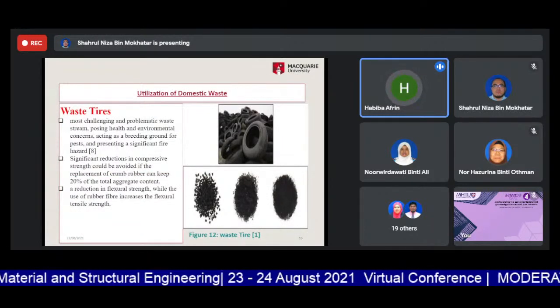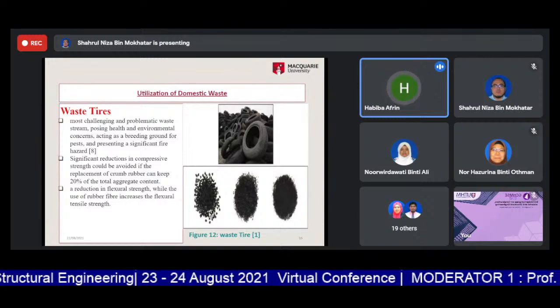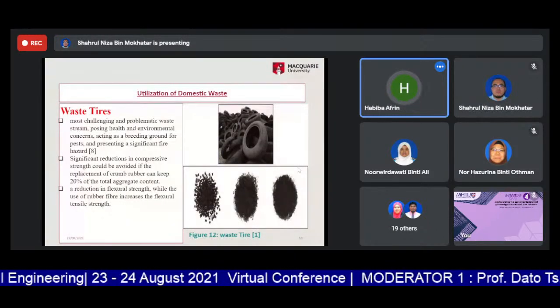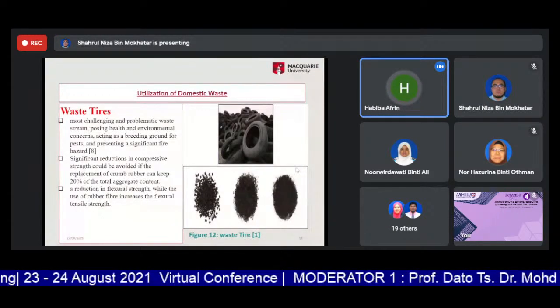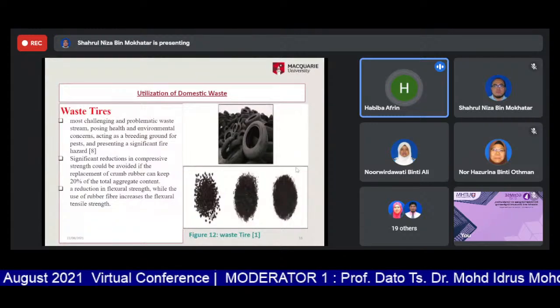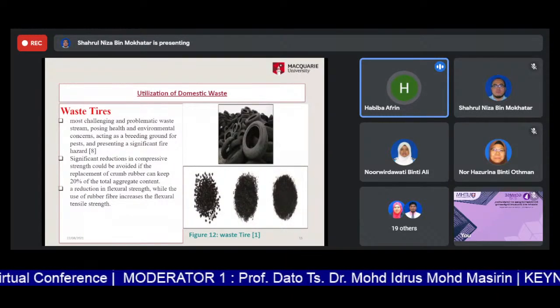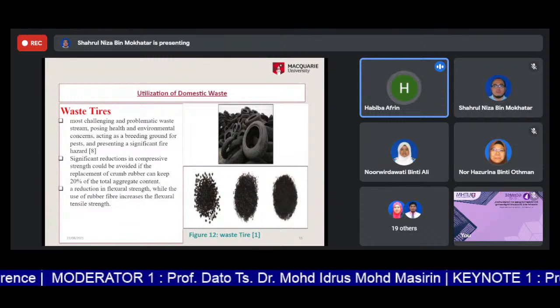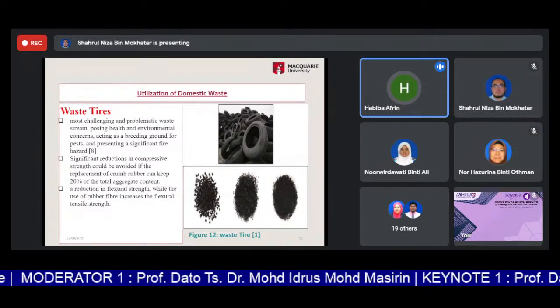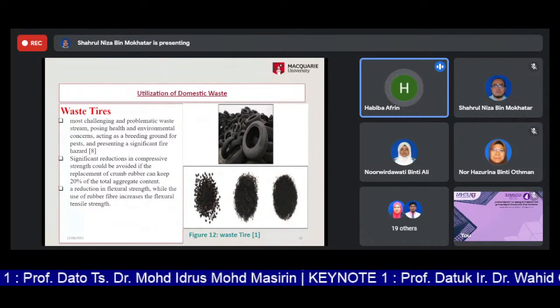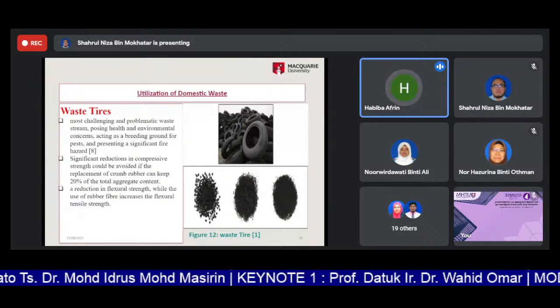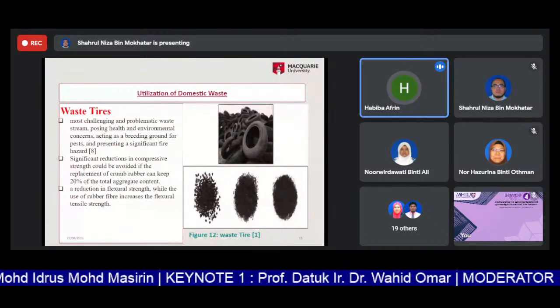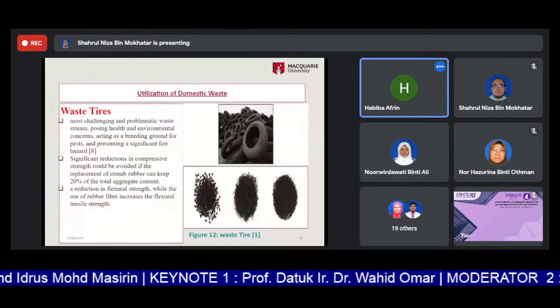We know about the tires. It is the most problematic waste stream, posing health and environmental concerns, acting as a breeding ground for pests and presenting a significant fire hazard. Significant reduction in compressive strength should be avoided if we replace the crumb rubber at 20% of total aggregate in concrete. There is a reduction in flexural strength, while the use of rubber fiber increases the flexural tensile strength as well.